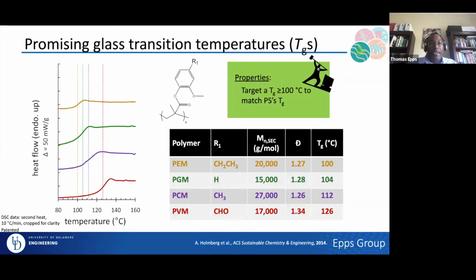So in this particular case, we had several criteria that we wanted to hit. As I mentioned earlier, one of the key things was, do these materials have glass transition temperatures around or greater than 100 degrees Celsius? So just showing some DSC data on the left, the curves are shifted vertically for clarity. But the key point is basically in the right-hand chart in the rightmost column.